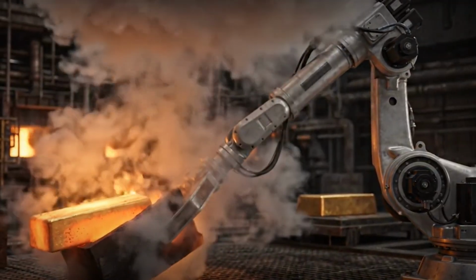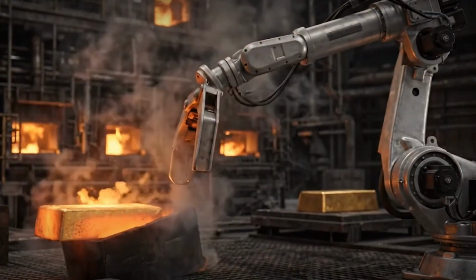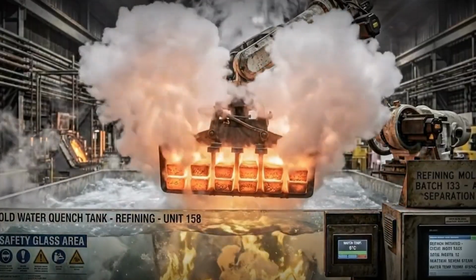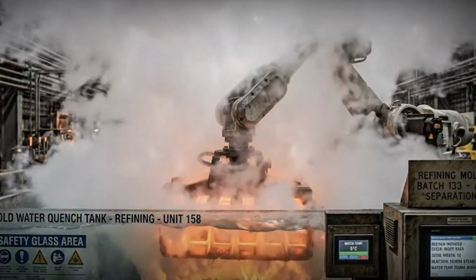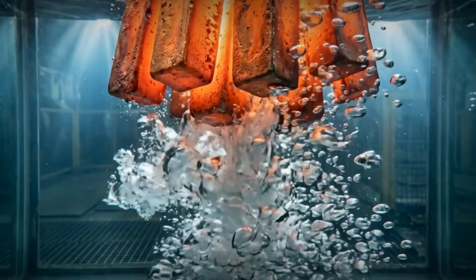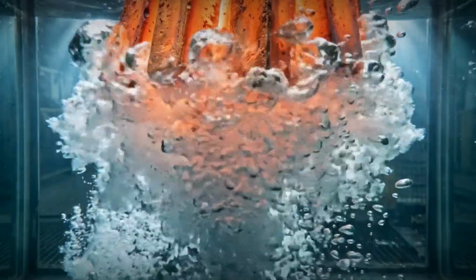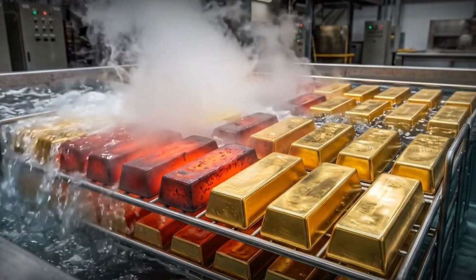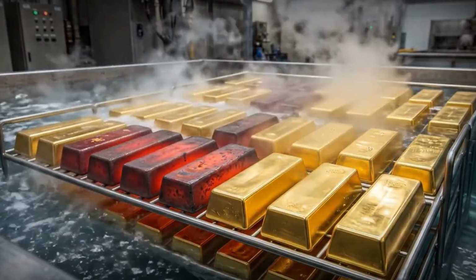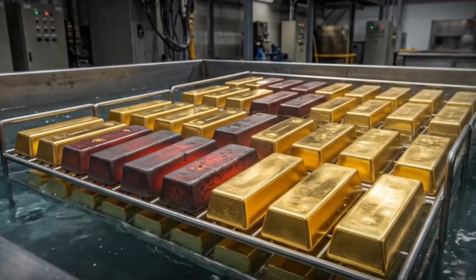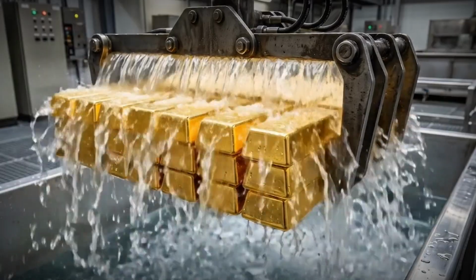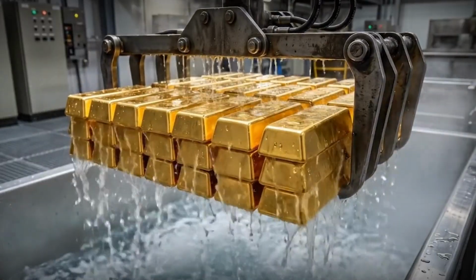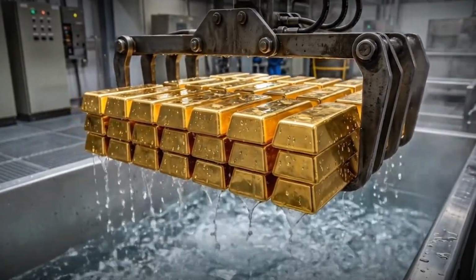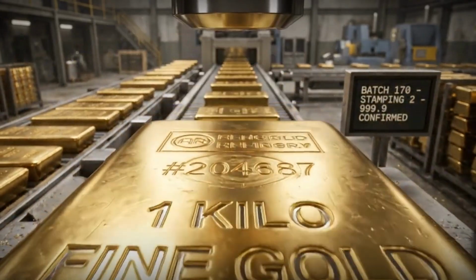At the refinery, doré bars undergo either the Miller chlorination process, where chlorine gas is bubbled through molten gold, reacting with impurities and driving them to the surface as chloride slag, or electrolytic refining, where gold is dissolved in an acid bath and redeposited in pure form through electrical current. Either method produces gold at 99.99% purity, 4 nines in the industry shorthand. The refined gold is cast into the standardized bars that trade on global markets, each one stamped with weight, purity, serial number, and refinery mark, each one meeting the London Bullion Market's good delivery standard.